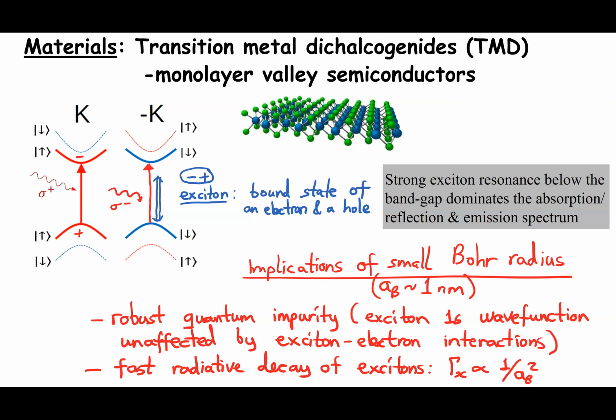The second implication is that the excitons live very short, because the lifetime of the radiative decay is inversely proportional to the oscillator strength, which is proportional to the reciprocal Bohr radius squared, which means that the excitons only live for picoseconds. So they have very little time to probe what is going on.